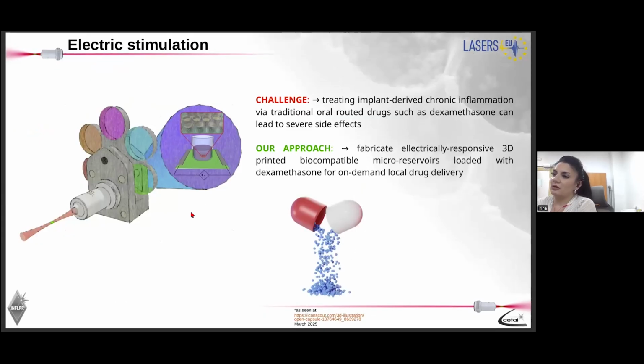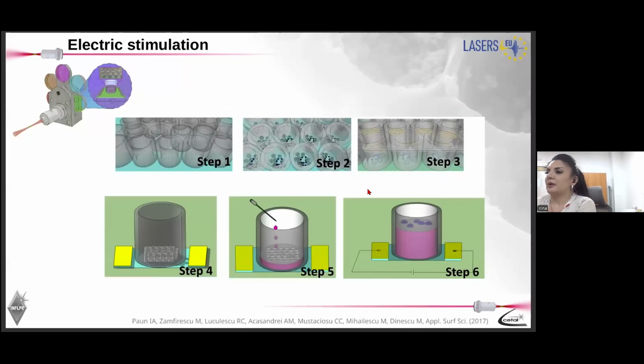Then we looked in another direction to see what happens with bone implants in general. These are affected in many cases by chronic inflammation after implantation, of course. And this is treated by administering anti-inflammatory drugs such as dexamethasone. But dexamethasone is generally administered by oral routes, which are toxic for the body and have severe side effects. We tried to respond to this difficulty by fabricating very small microreservoirs to be located next to the implant, and also to load these microreservoirs with dexamethasone and to release the dexamethasone on demand and on specific time scales by applying external electrical stimuli on these structures. As such, these are the main steps we took here.